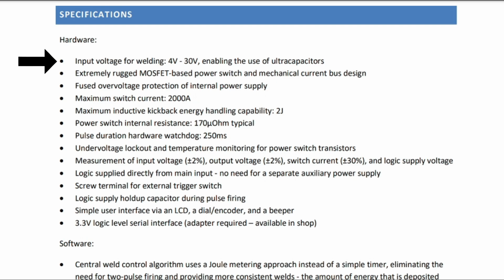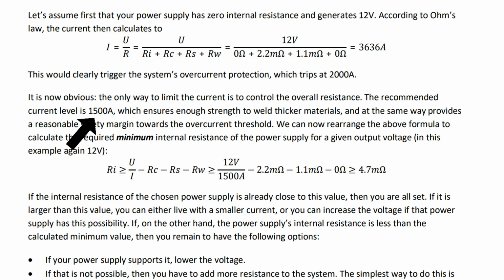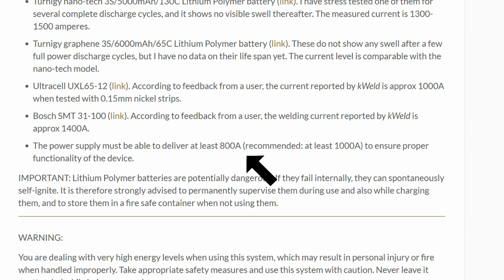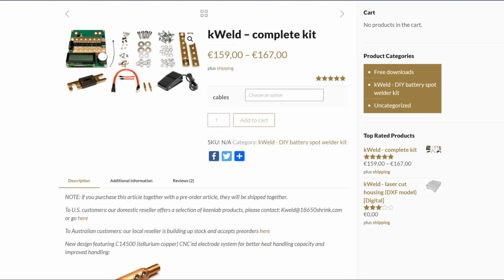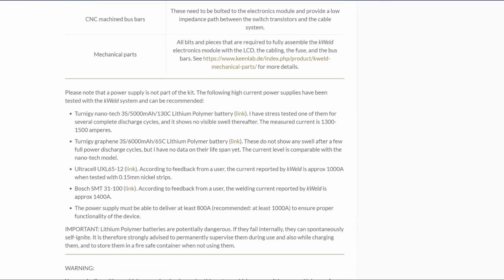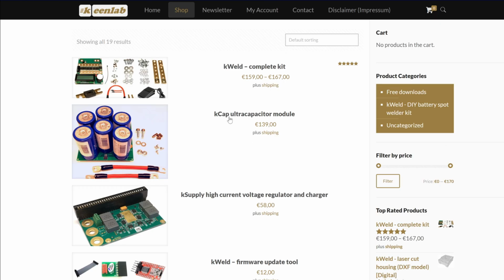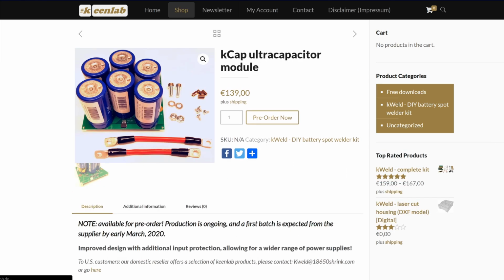Now the k-weld has a fairly wide input voltage range of 4 to 30 volts, and it can handle, as we've mentioned, up to 2000 amps of current, with the sweet spot being 1500 amps, and with a minimum of 800 amps. Anything below 800 and the k-weld won't allow you to weld. Basically there are two options. Select a LiPo or lead acid battery from the recommended list, or the better option in my opinion is to use super or ultra capacitors, which KeenLab sell as a separate kit set if you're interested.